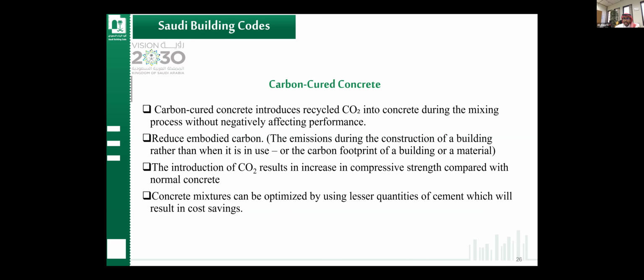Another promising innovation is carbon cured concrete, and this approach captures CO2, which is injected during mixing or curing. This permanently sequesters carbon while improving compressive strength. Stronger concrete allows for lower cement content, further reducing the emissions.